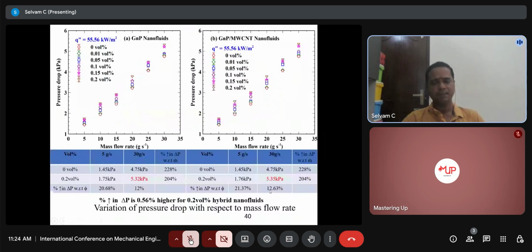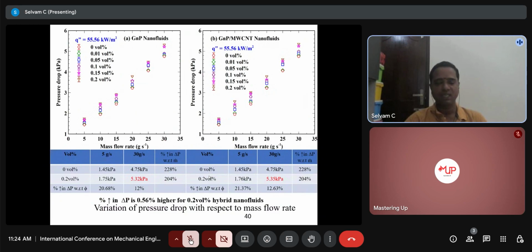Pressure drop, as expected, is increasing with respect to the volume concentration of the nanoparticle. But at the same time the pressure drop is not increased more as compared to other nanoparticles, because compared to metallic or metallic oxide nanoparticles, graphene and multi-wall carbon nanotubes have less density. Multi-wall carbon has a higher value as compared to GNP, but it is slightly higher, so it won't be a big issue in the pressure drop. At the higher concentration of GNP, we observed 5.32 kilopascal pressure drop, but here 5.35, that's it, with the use of hybrid nanofluids.